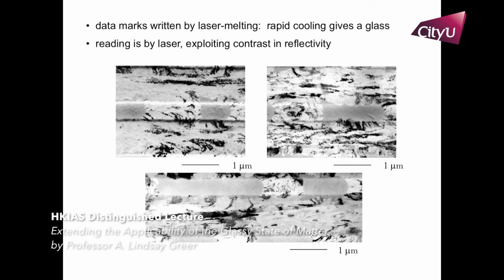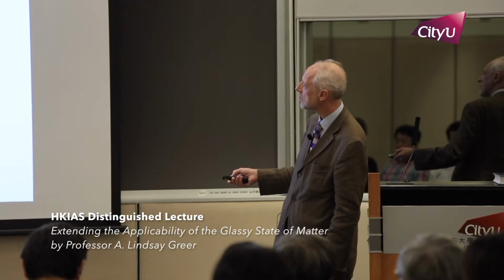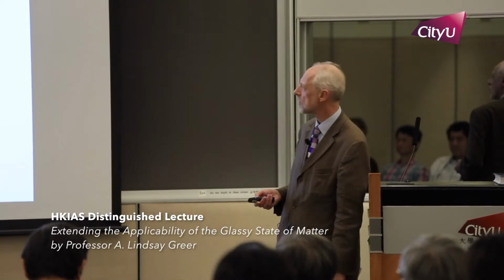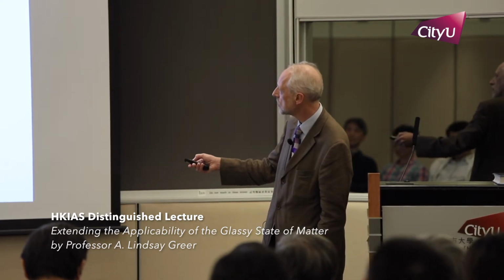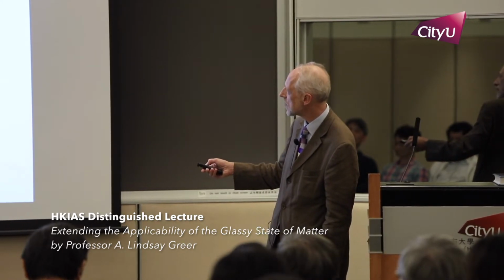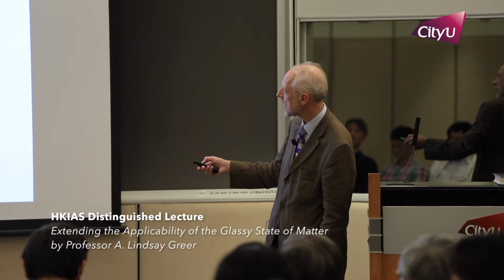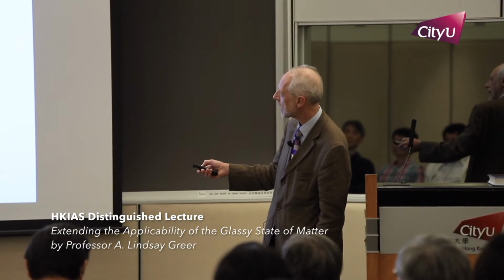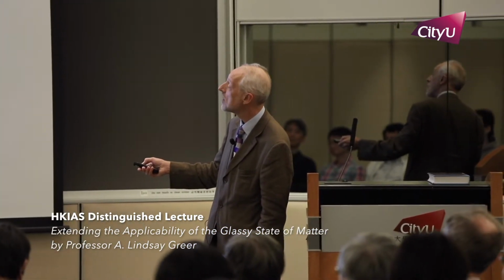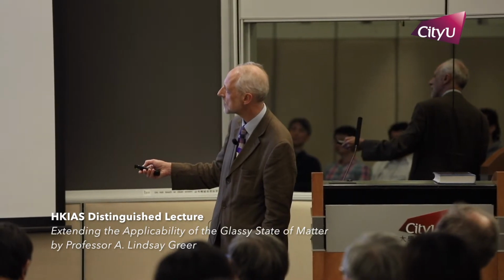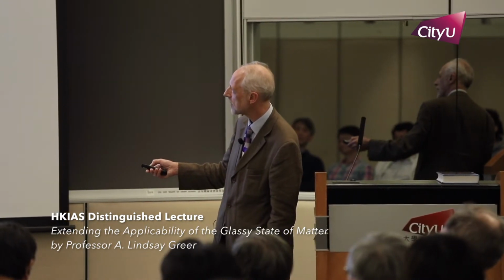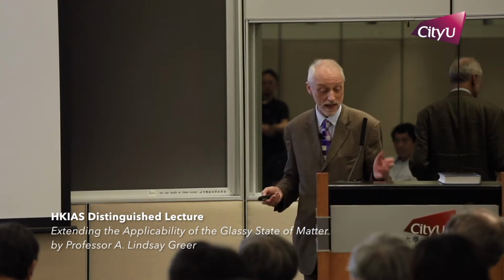So this squirrely pattern of black and white is the grain structure of the thin film, crystalline. That's what you have in your natural disc. These tracks are the grooves, and the lasers write data in the form of these sort of fishtail-shaped things, which lack the internal black and white pattern of the grains, because that is glassy, cooled at a rather high rate, possibly of the order of 10^9 degrees per second in this system. And it cools into the glassy state, and that's how you write your data.